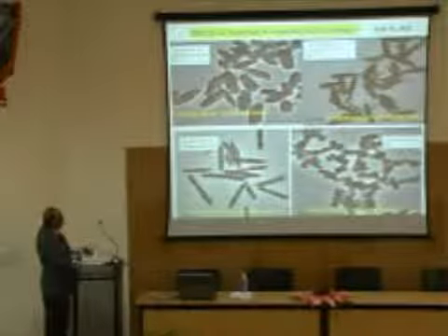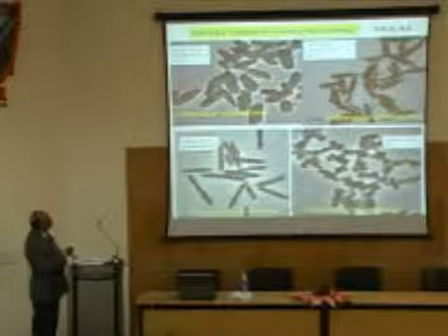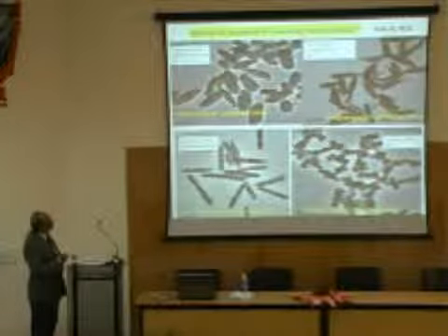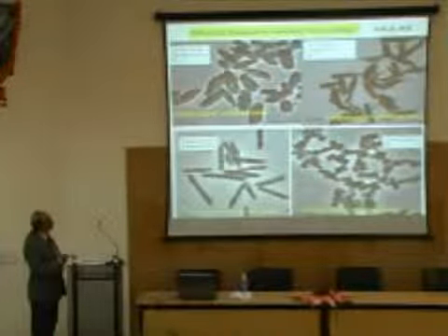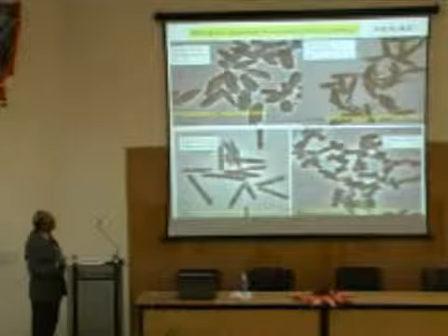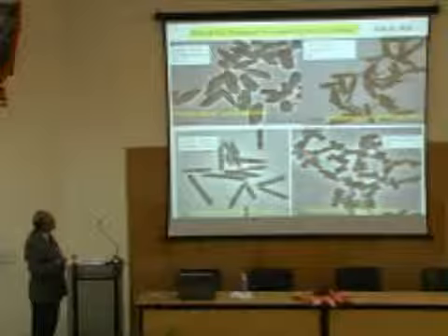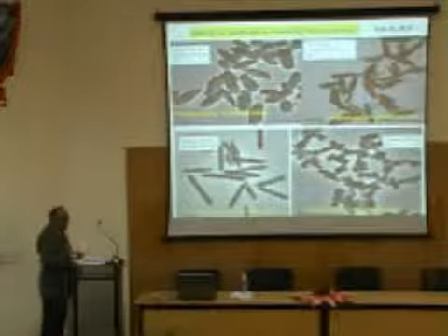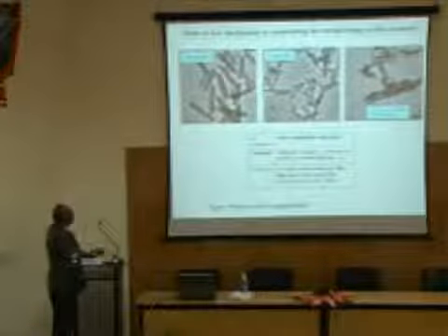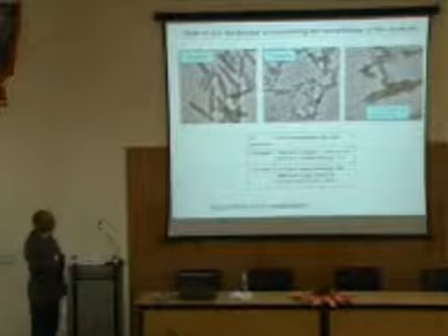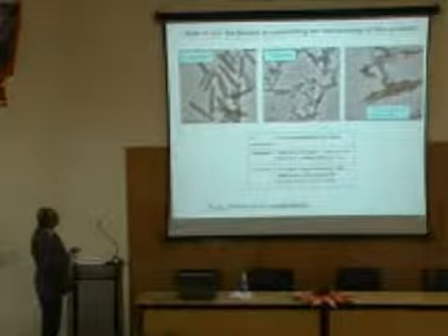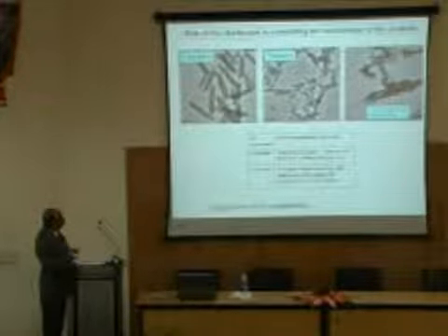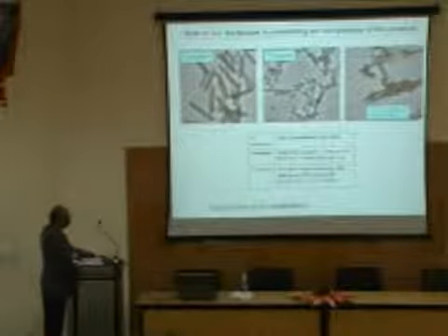This is again to show another role of another chemical. I didn't get into that. It's called a co-surfactant. If you modify the co-surfactant also, you can modify the width of the rod. Here you can see the aspect ratio is larger than this. Here the length and breadth are becoming nearly equal. Okay, so controlling the nanostructures can be done by this method easily. This is again by changing co-surfactant, you can go from longer, higher aspect ratio to smaller aspect ratio.